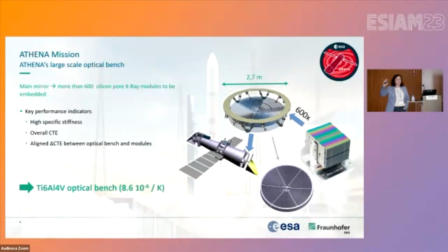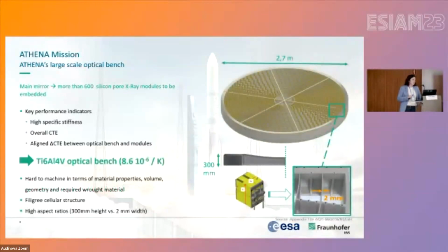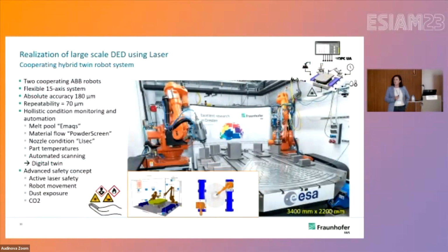Other parts will address this optical bench in aluminum by combining conventional manufacturing and milling. But concerning the oxidation issues and also reflection issues, we didn't follow the path with aluminum, but addressed titanium as the alternative in our case. Obviously, titanium leads to other issues like milling, which is also quite challenging. The oxidation issues, so we studied the introduction of a flooded atmosphere or local shielding to the process. And then you will see later on what are our choices for the fabrication of the optical bench.